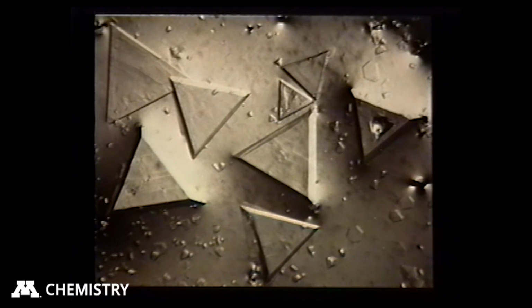But we have an easy way to tell whether they're truly trigonal or not truly trigonal. And that is putting it under the cross polarizers and rotating it. And when you do that, this crystal extinguishes. So it truly does not have a 3-fold axis coming out of it, even though the morphology suggests that these are pseudo-trigonal, and the morphology is reflecting the symmetry of individual planes of molecules rather than the symmetry of the entire crystal structure.